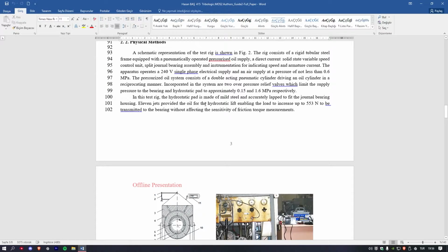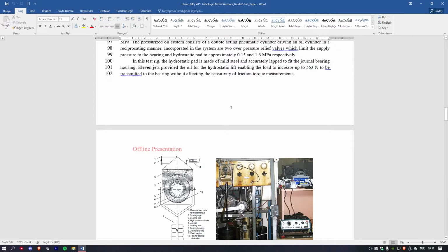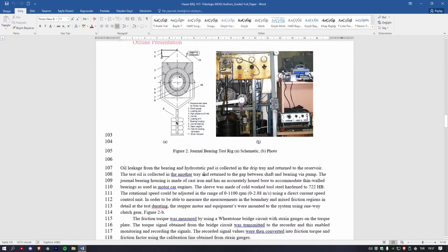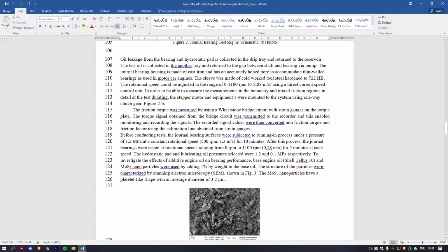In this test rig, the hydrostatic pad is made of mild steel and accurately lapped to fit the journal bearing housing. 11 jets provided the oil for the hydrostatic lift, enabling the load to increase up to 553 Newton to be transmitted to the bearing without affecting the sensitivity of friction torque measurement. The friction torque was measured by using Wheatstone bridge circuits with strain gauge on the torque plate. The torque signal obtained from the bridge circuit was transmitted to the recorder and this enabled monitoring and recording the signals.